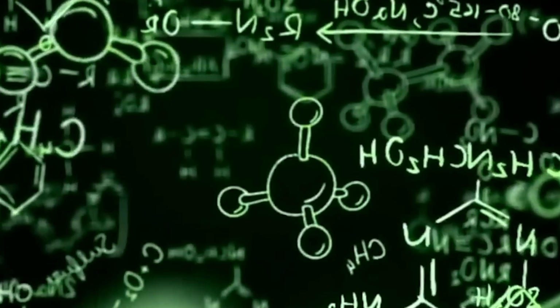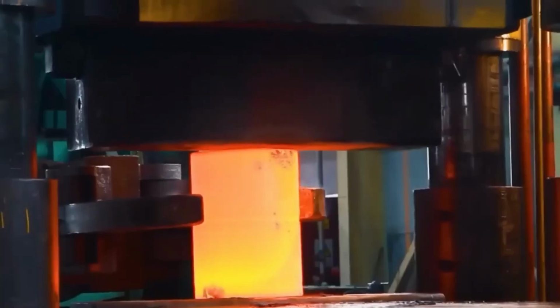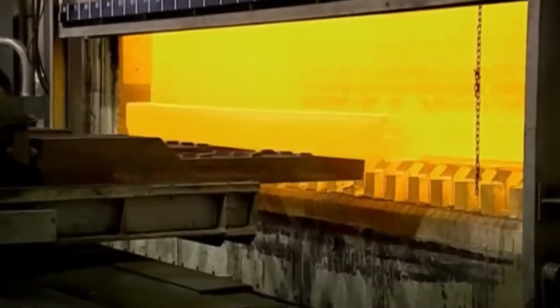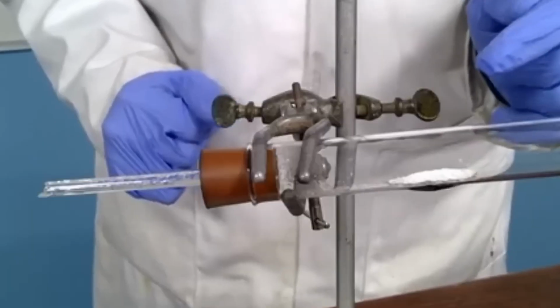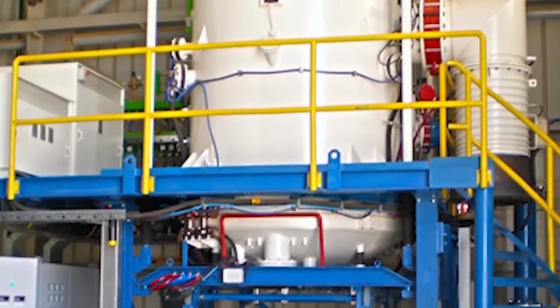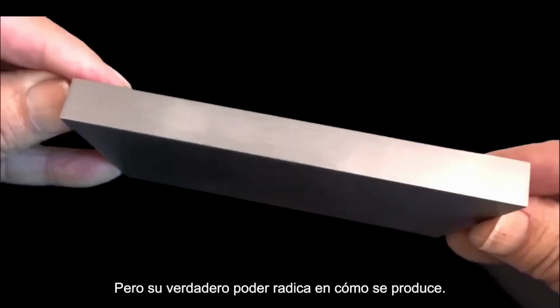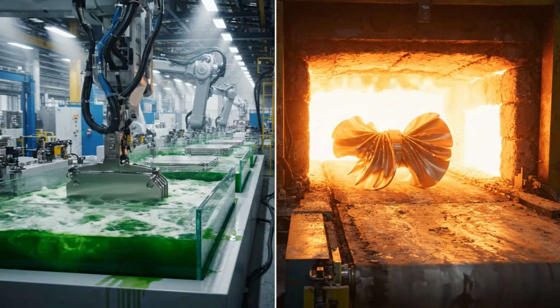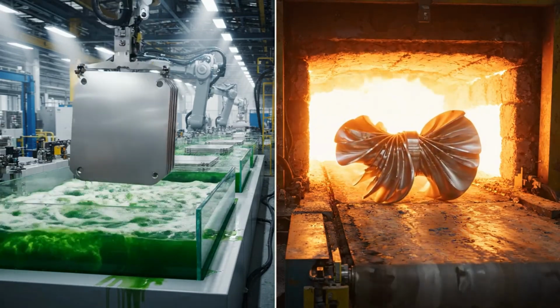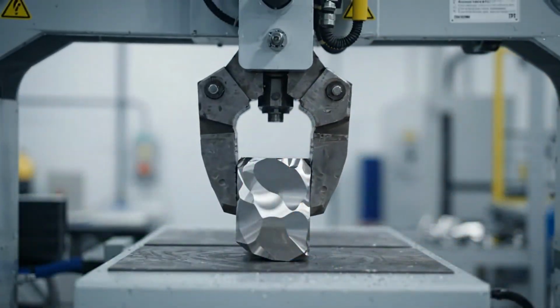Its oxygen, nitrogen, iron, chlorine, magnesium, and other elements are checked. Some fractions can be used to produce commercially pure titanium, while others are mixed with alloying elements. One of the most well-known grades is Ti6Al4V, an alloy with aluminum and vanadium widely used in aerospace, medical implants, high-performance components, and parts subjected to severe loads. The exact composition depends on the end use. Pure titanium is highly resistant to corrosion, but alloys improve its mechanical strength and performance at high temperatures.